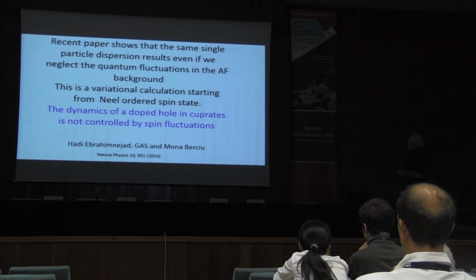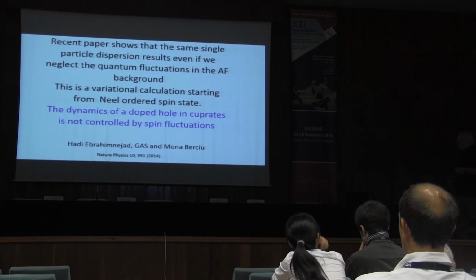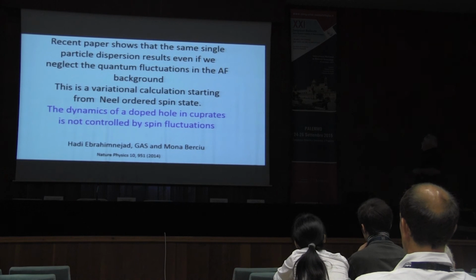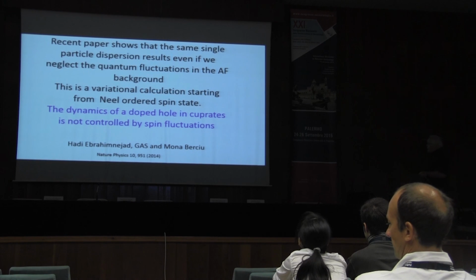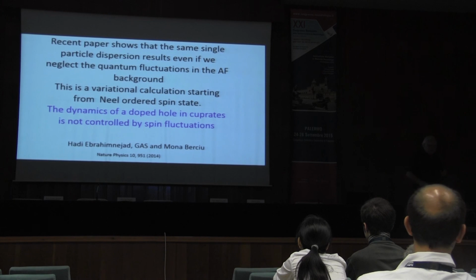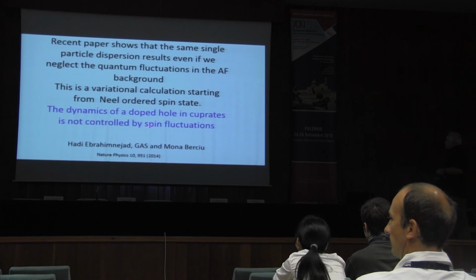But at least we started with a picture in which we really had holes on oxygen, and then did a very big exact diagonalization that could get us the Zhang Rice singlet state, if that was the correct one, but it didn't. It gave us this composite state. Now in a recent paper, we've also shown that the single particle dispersion results even if we neglect the quantum fluctuations in the antiferromagnetic background. So in the background, the quantum fluctuations are apparently not important. That's what the exact diagonalization and this other calculation show you.